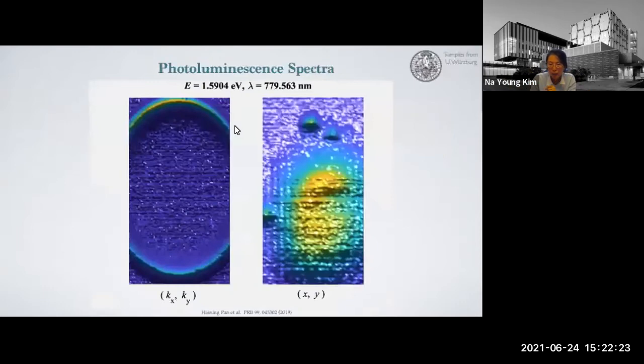So let's take a glimpse of the experimental data. We are measuring the photoluminescence spectra. What does that mean? We have a sample, we shine the laser, photons, and then our device, the gallium arsenide-based microcavity exciton-polariton, emits fluorescence. That's why we call it photoluminescence. We are looking at the luminescence to identify information about the system in the presence of the honeycomb lattice, in terms of momentum, in terms of energy, and also in the XY plane.